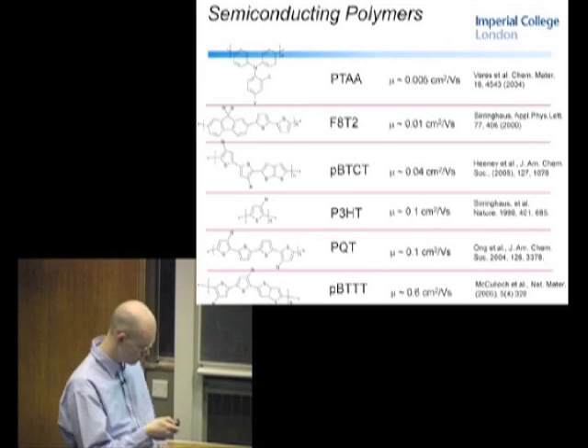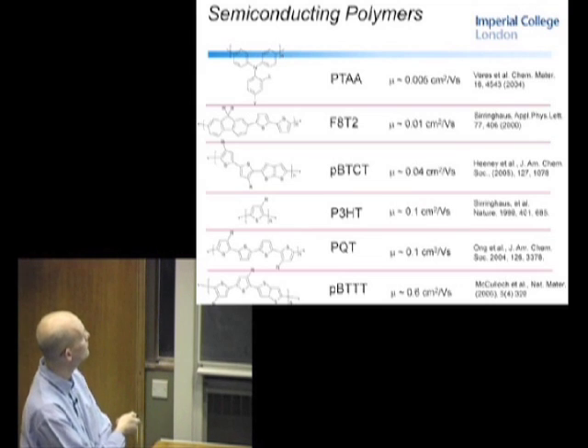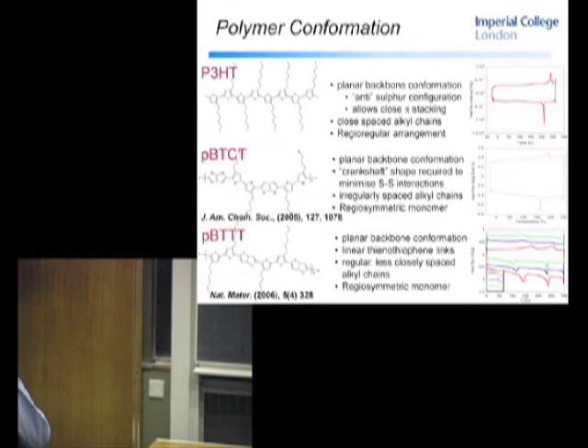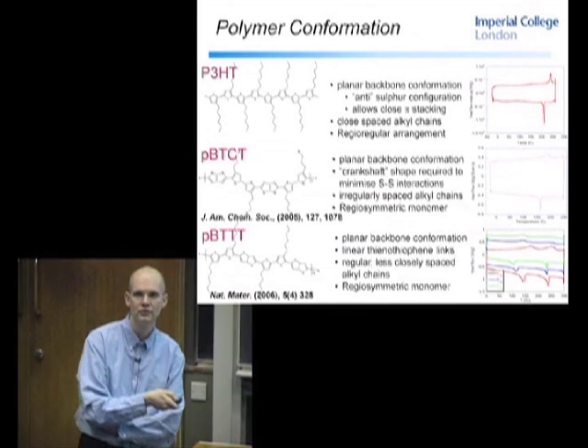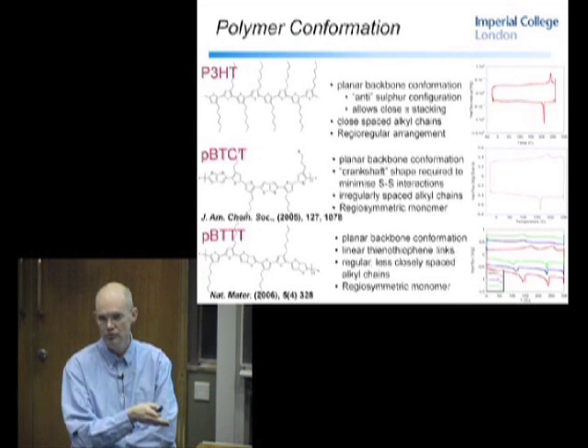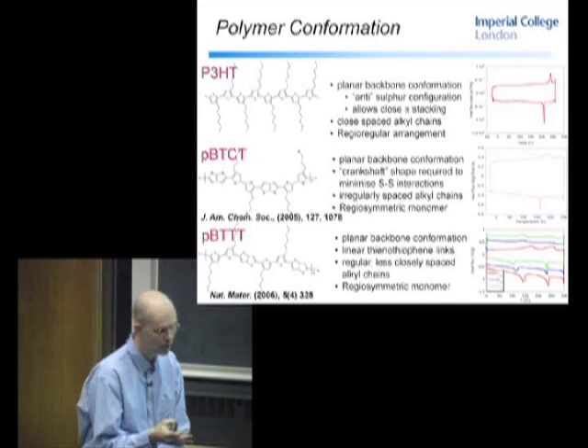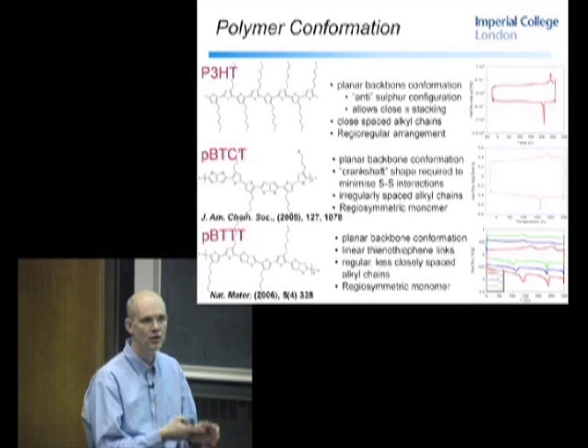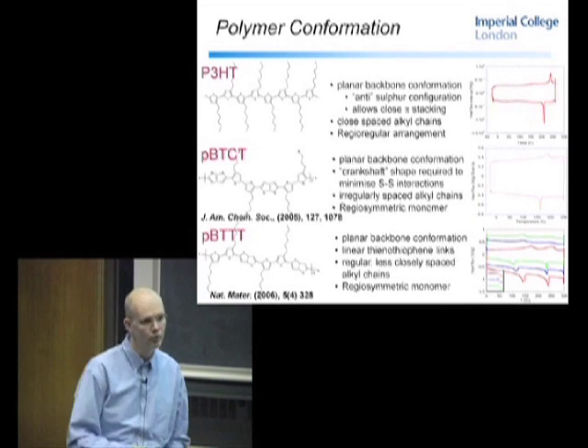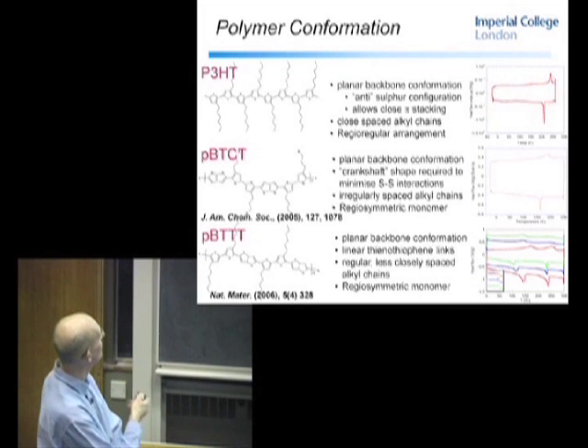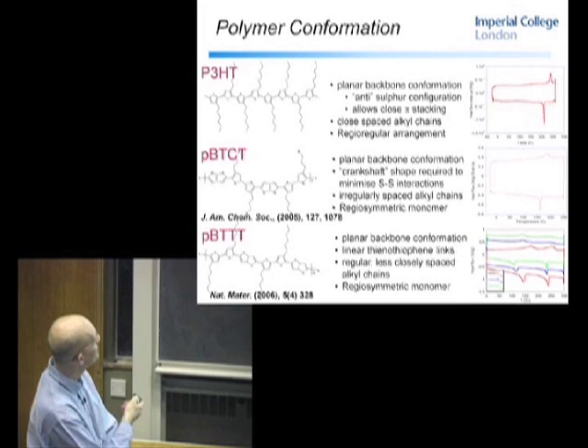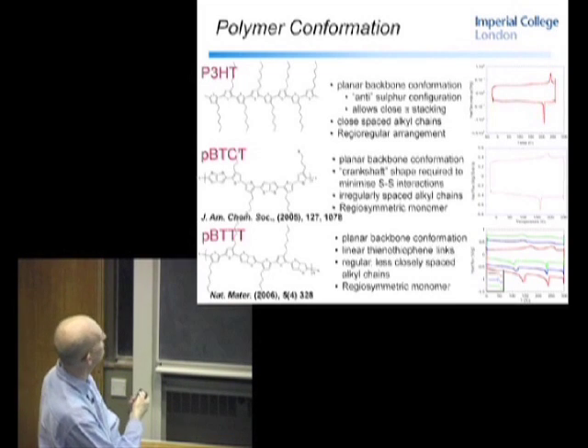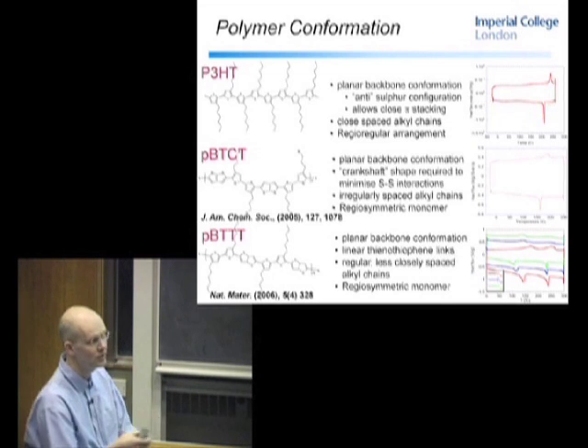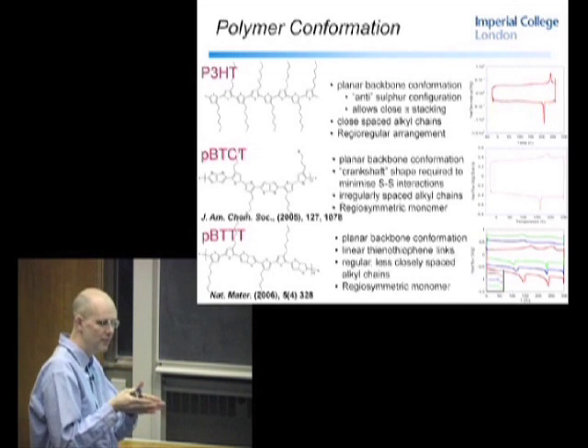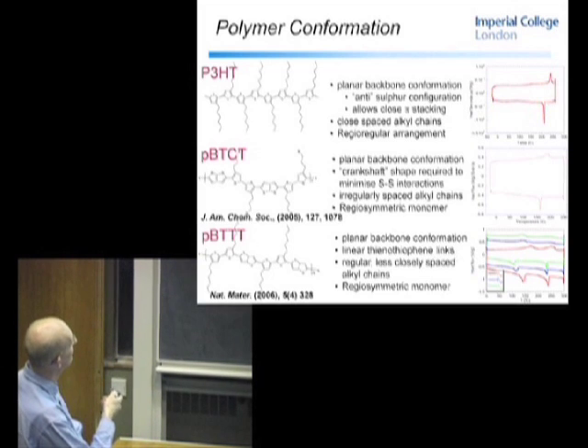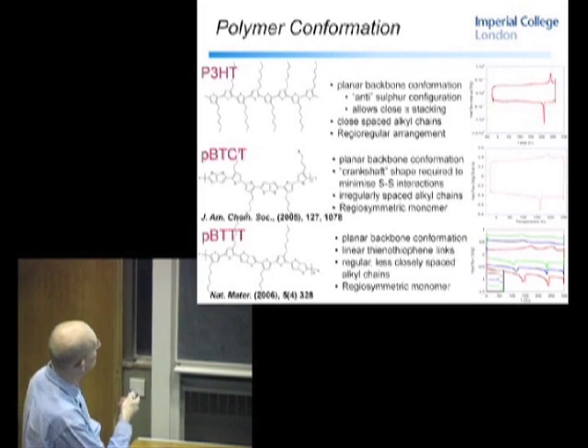And this is going to be the material that I'm going to talk about now, probably for the next 15 minutes or so. So when we think about how we're going to design polymer semiconductors, we take a lesson from high performance small molecules. And what you see clearly here is that crystallization, organisation, long range positional order is very important. And so what we've been trying to do with these polymer structures is to make very crystalline ordered materials. So we try and planarise the backbone to get this pi-pi stacking, so that the pi-pi distances are 4 angstroms or less. So we have to pay particular attention to the conformation.